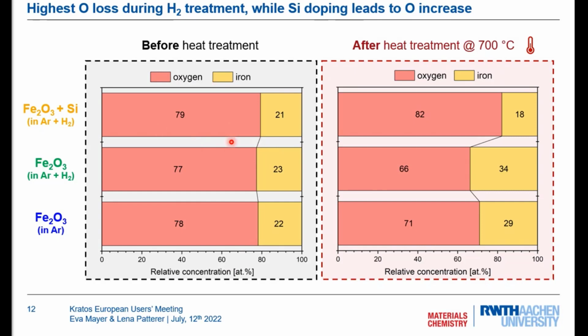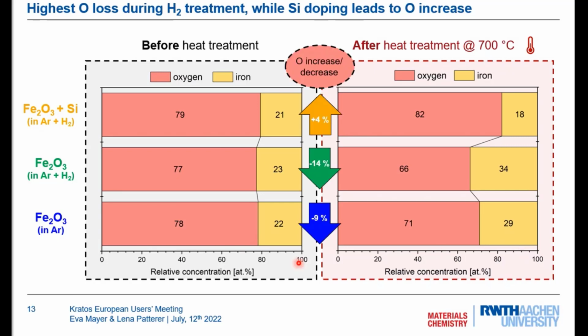Beforehand, it was also very similar to the other ones, but afterwards there is a way higher oxygen to iron ratio. And as you can see here as a summary, the sample that was heated in argon has a percent decrease of 9% in oxygen, while the one that was heated in argon plus hydrogen has a 14% decrease. And the sample containing silicon has even an increase in 4% of oxygen.